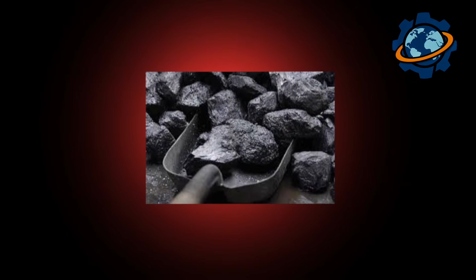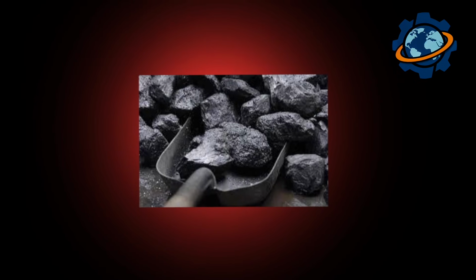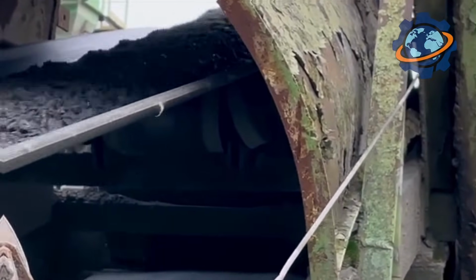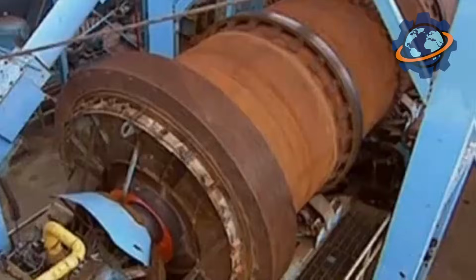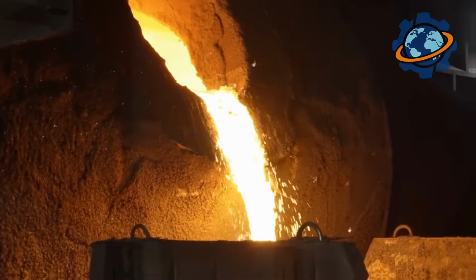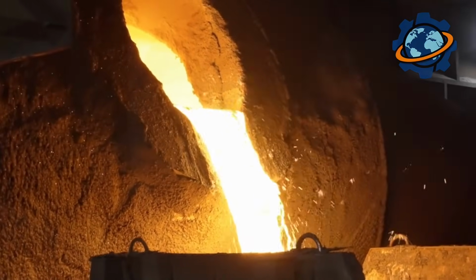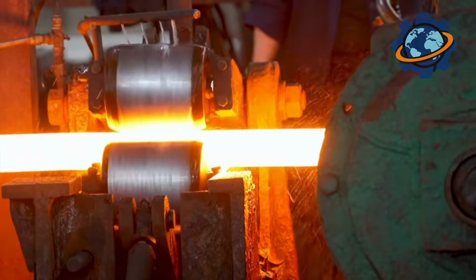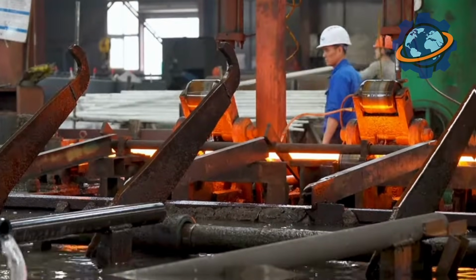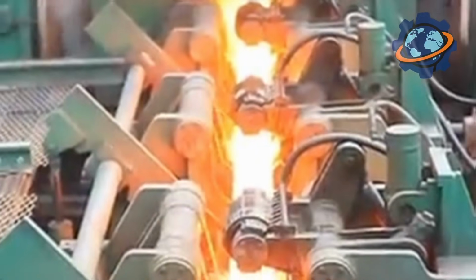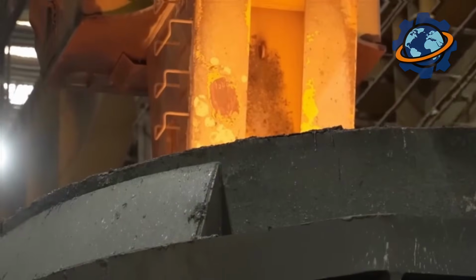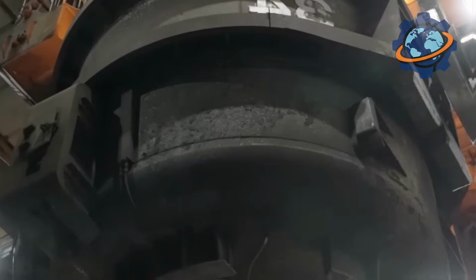And so, traveling from explosions and 2,000-foot-deep quarries through giant crushers and magnetic separators, through 300-foot-tall blast furnaces at 3,600 degrees and converters where oxygen burns out carbon in 20 minutes, through rolling mills where 8-inch slabs become millimeter-thin sheets, steel emerges, the metal that built civilization.